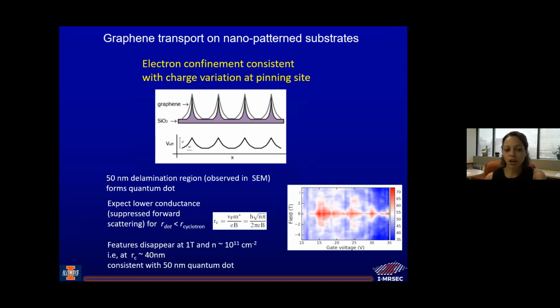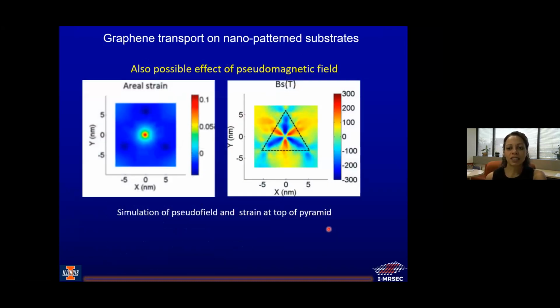It's a pinning region, but we also see that we have possible effects of a pseudo-magnetic field, which was one of our original goals. Okay, so how do we know we have a pseudo-magnetic field? Well, we worked with our theory collaborators to look at simulations, and you can see that when they simulated the strain at the top of the pyramids, they get a very high and localized areal strain at the top of these nano pillars, and they can also calculate a very high pseudo-magnetic field at the top of these nano pillars. And so that also will confine our carriers.